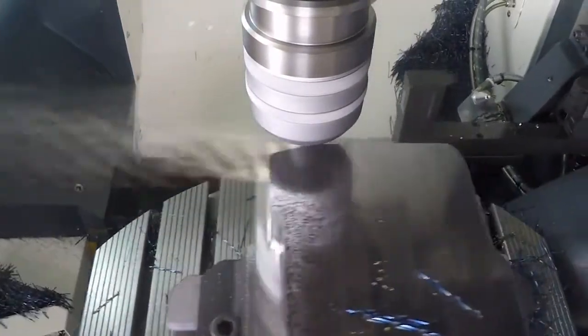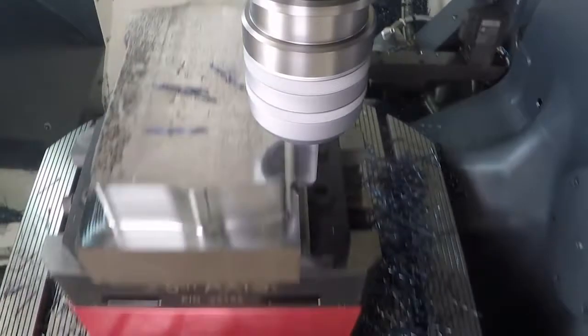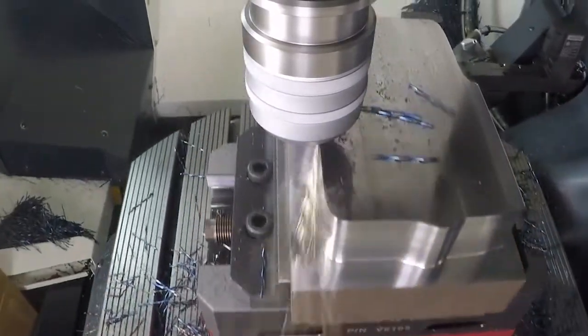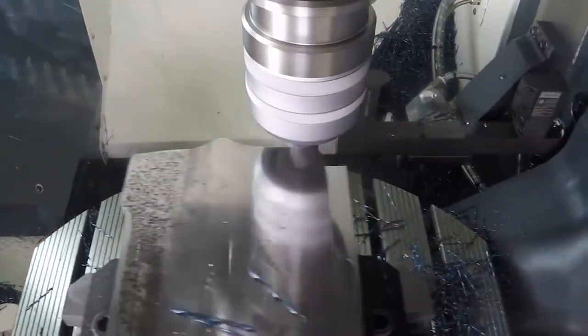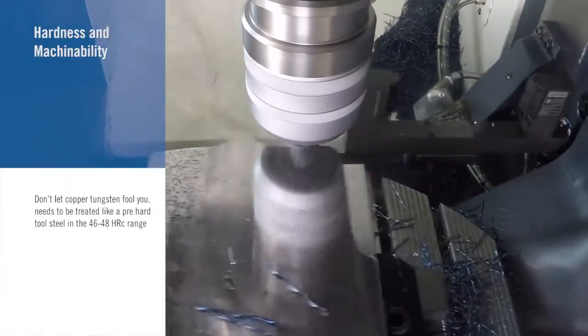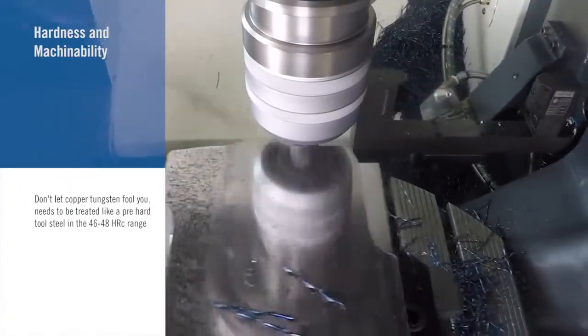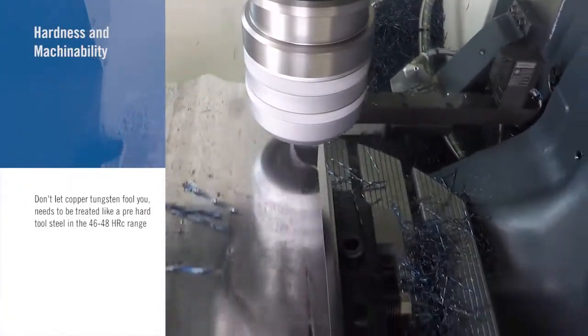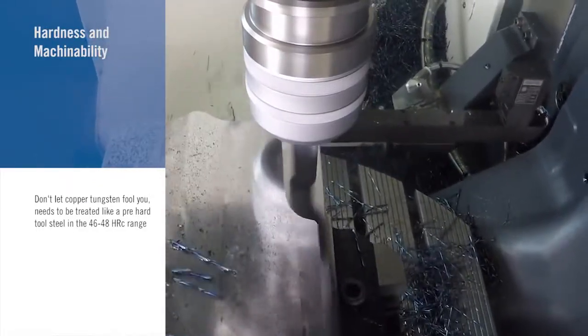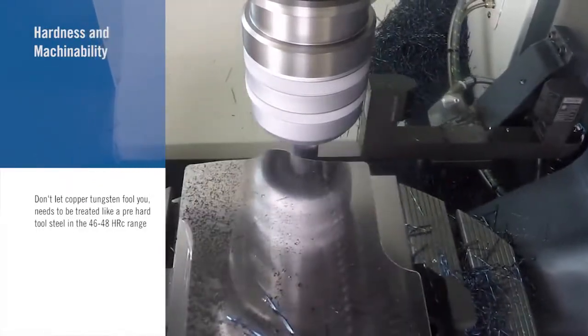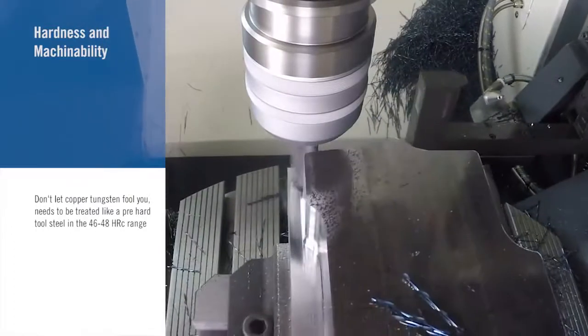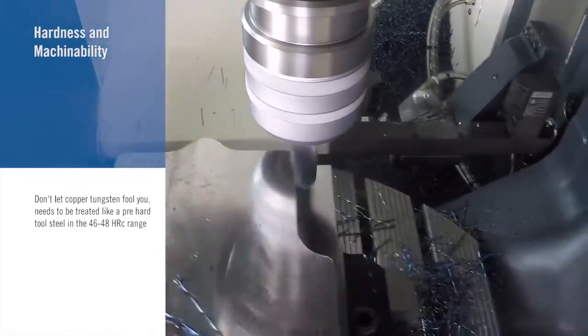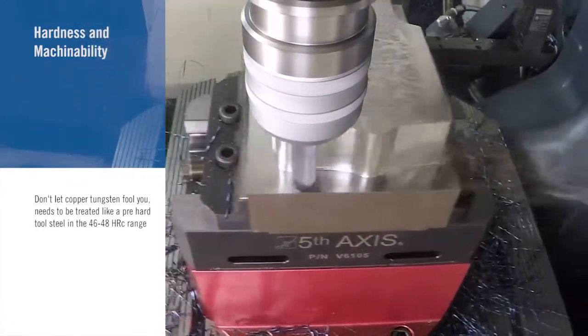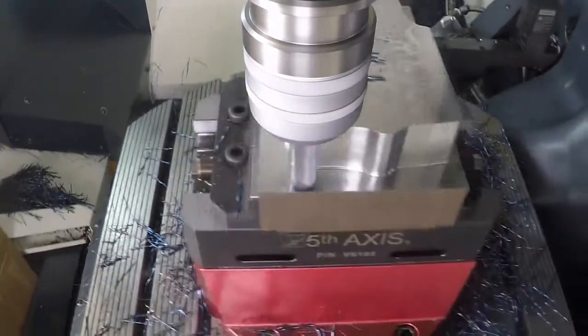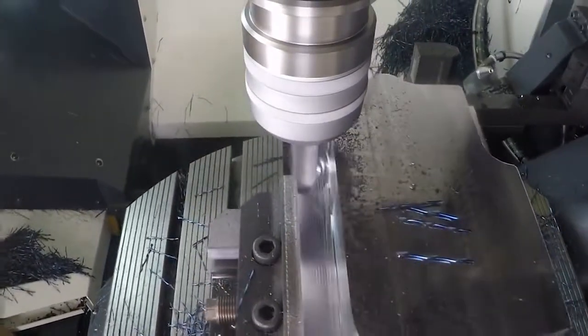Now, a material that's actually caused a lot of heartache for a lot of guys in the years I've been doing this is a material called copper tungsten. That's an electrode material that's used for machining carbide packing dies. And what'll get you is the fact that it says copper, but you also have to be mindful that there's tungsten in that material, and the tungsten makes it extremely abrasive. So as far as cutting tools go, I actually recommend cutting tools that are designed for doing 46 to 48 Rockwell, and then also the speeds and feeds to go with them. So just keep that tip in mind when you're machining copper tungsten.